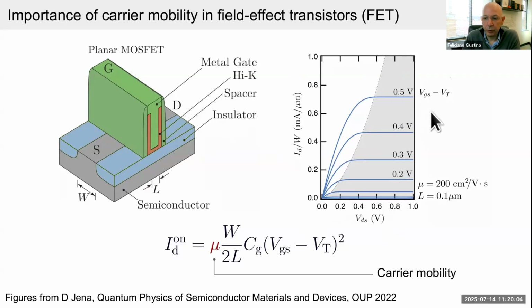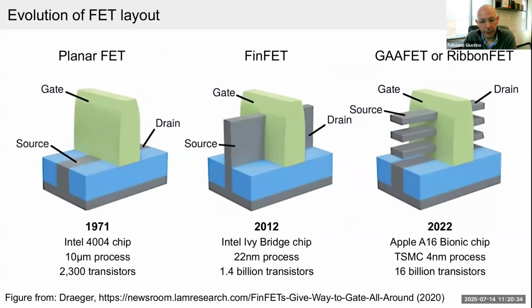Now, the important part in this story is that in order to make the transistor more efficient, meaning that you can switch it with a lower potential and it generates less resistive losses, you need to basically improve this single device descriptor, which is the carrier mobility. So this simple parameter mu is a materials-level parameter, and it is actually a descriptor of how fast electrons can move in a semiconductor once you apply an electric field, okay? So it is important to have this number as high as possible.